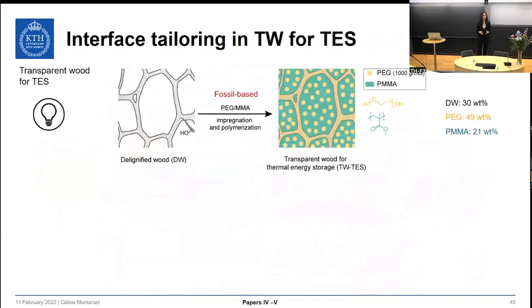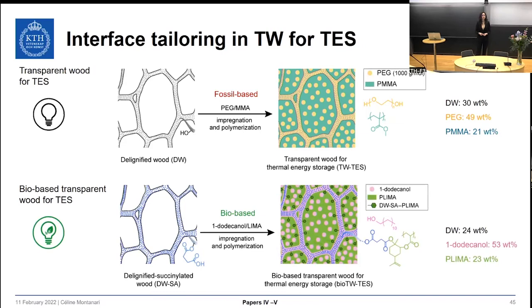In the proof-of-concept, the starting material is delignified birch. We selected polyethylene glycol (PEG) as the phase change material, mixed with methyl methacrylate, followed by in-situ polymerization. The final material is a transparent wood with three phases: delignified wood reinforcement, PEG as phase change material, and PMMA polymer phase. We selected PEG with a low molecular weight of 1000 g/mol so it can be distributed both in the lumen and in the cell wall. In the bio-based design, the starting material is succinylated and delignified birch; a bio-based phase change material, 1-dodecanol, was mixed with bio-based LIMA monomer followed by in-situ polymerization, with PLIMA forming covalent links with the wood substrate.